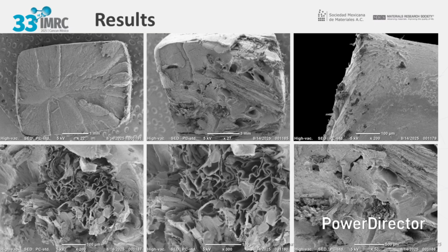2. Internal fiber structure, intermediate and high magnifications, 200x, 300x. Higher-resolution micrographs reveal the typical cellular morphology of natural fibers: elongated lumens, multilayered cell walls, and structures collapsed during specimen preparation. These microstructural characteristics in sugarcane bagasse give the reinforcement a low specific weight, but simultaneously generate stress concentration sites and facilitate moisture absorption, factors that can compromise the composite's dimensional and mechanical stability.